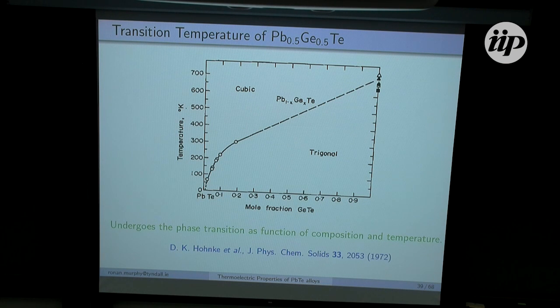Now, as I've mentioned a few times already, our calculations are DFT, they're done at 0 Kelvin. Our interatomic force constants are temperature independent. So unfortunately, we're not going to capture that phase transition as a function of temperature. But we will capture it as a function of alloy composition.